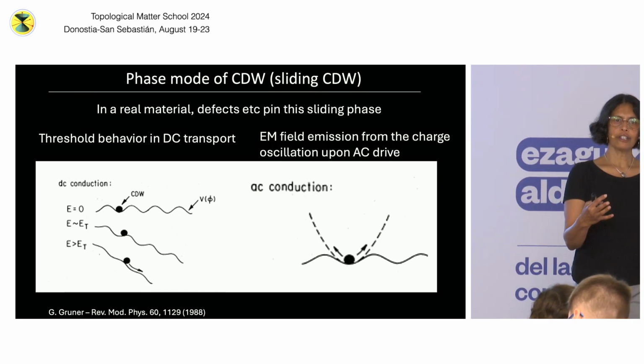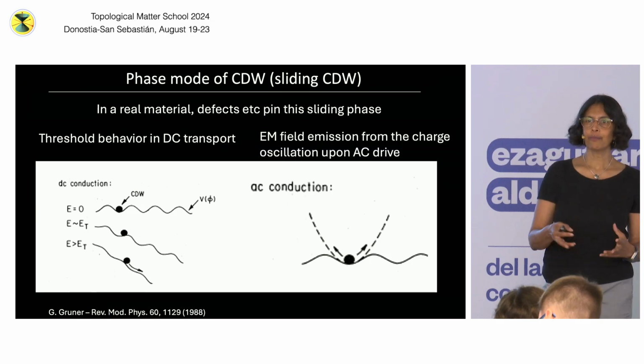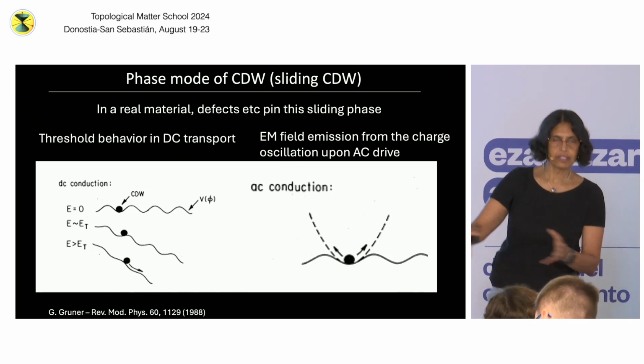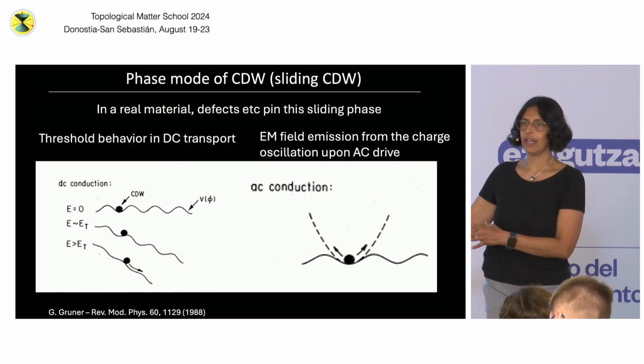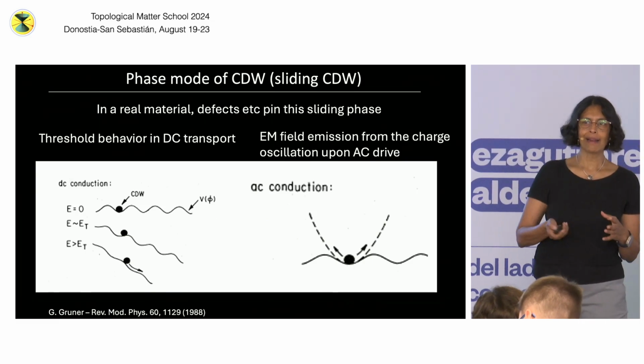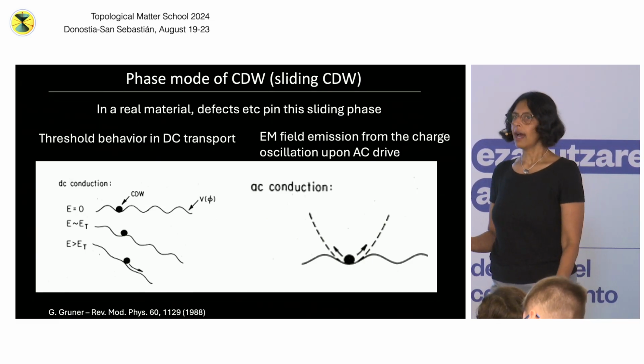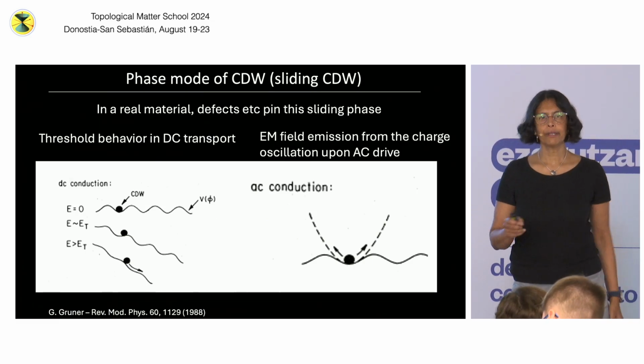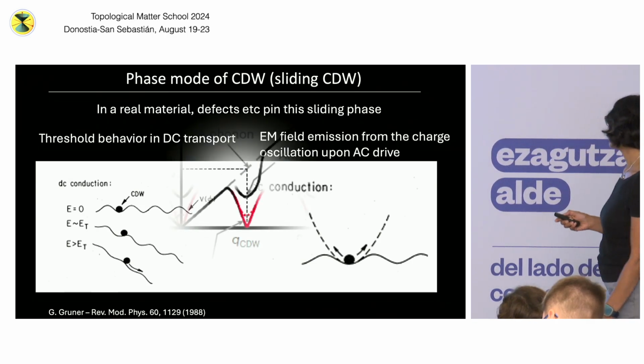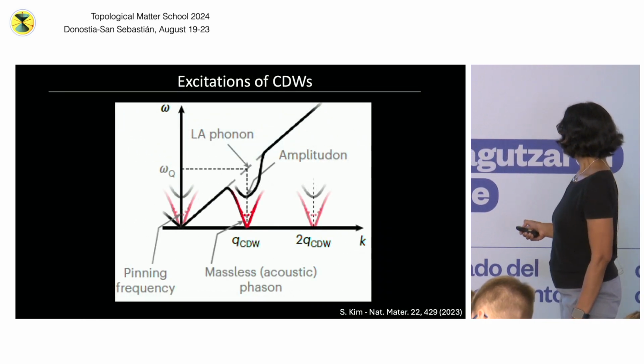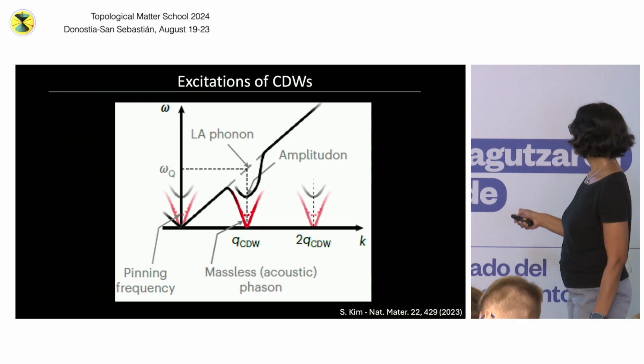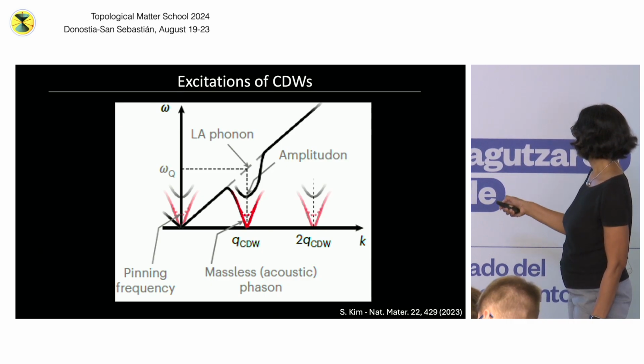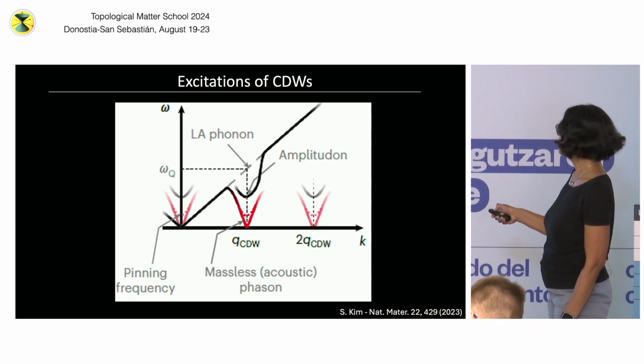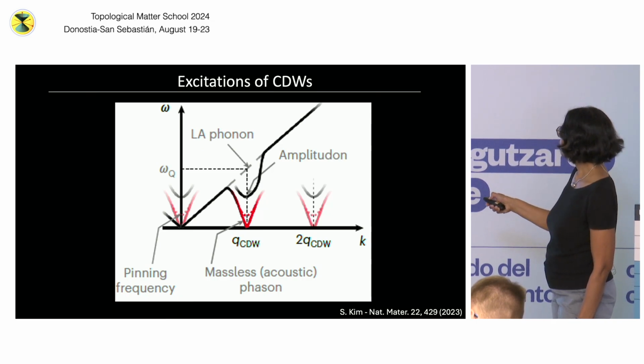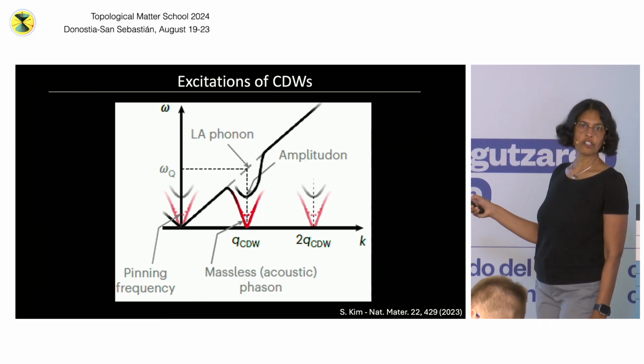But in a real material, the phase can be pinned by impurities. So if you want to move this charge density wave, slide the phase, you have to actually apply a little bit of force, okay? And so that gives the phason a tiny bit of mass, but usually it's not a big amount of mass. So in general, this is omega versus k, this is dispersion. You have this massless phase mode, and then you have the massive amplitude mode. That's the usual charge density wave.